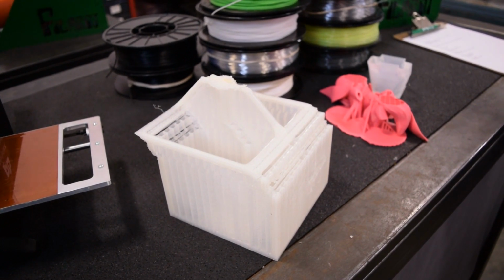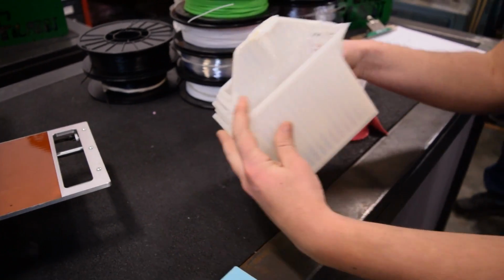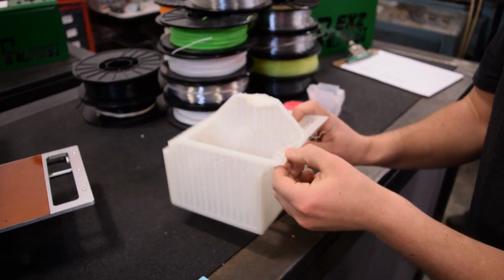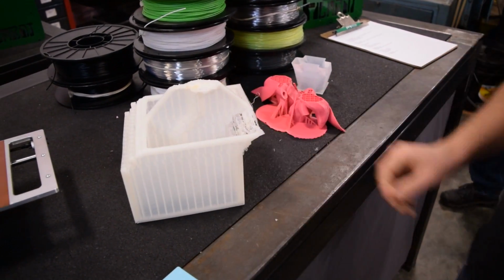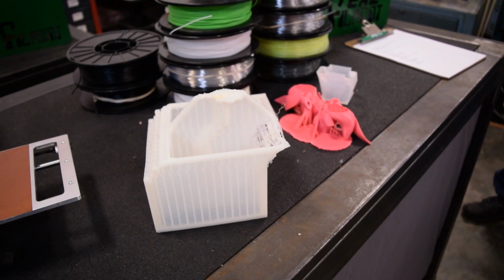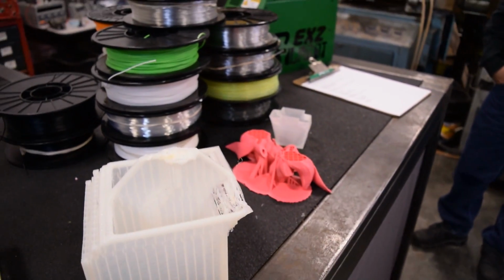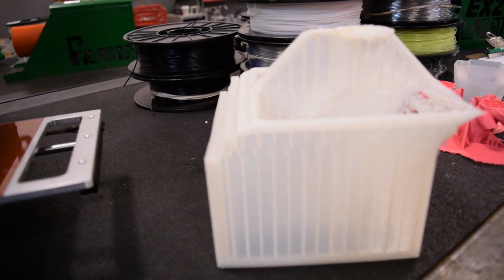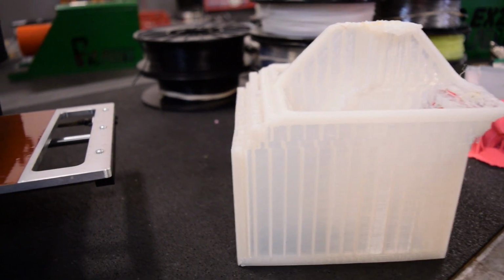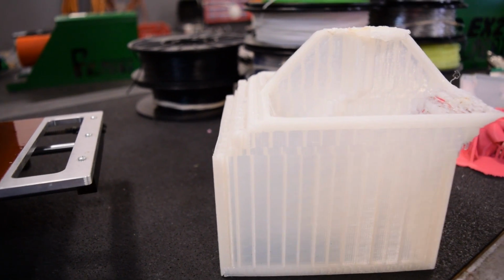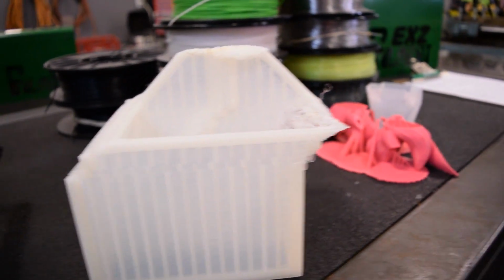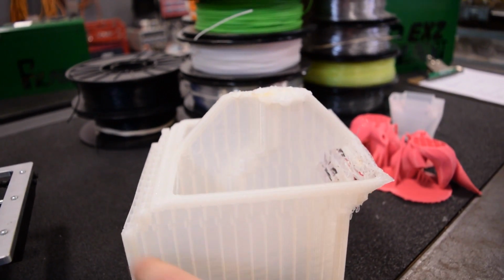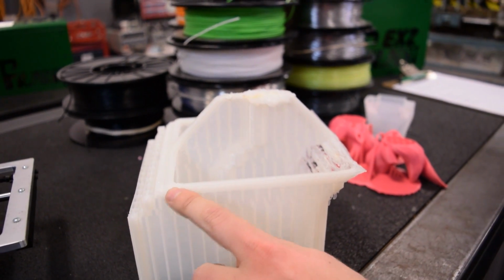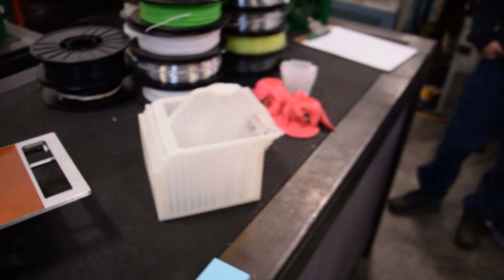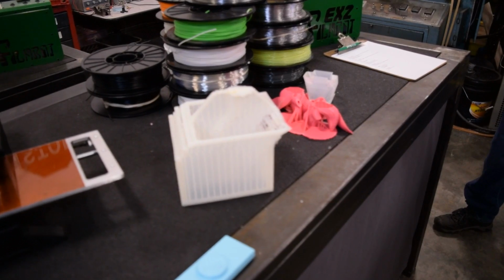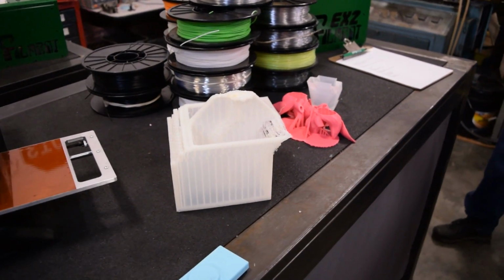and the nozzle will catch on the print and either knock it off the bed. Kind of like this here, right? Yeah, but that was because it skipped. So it'll either knock it off the bed, or it will catch and skip. And what happened here was it caught, and one of the axes skipped, and it started printing off to the side, and that happened actually a couple of times. Yeah, you can see probably 1, 2, 3, 4. But those two issues are mainly caused by the polymer shrinking and the nozzle catching on the edge of the print.